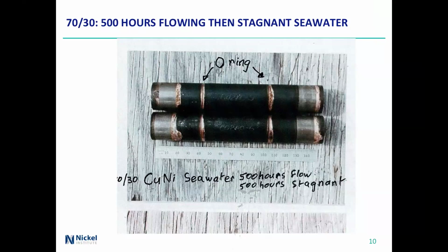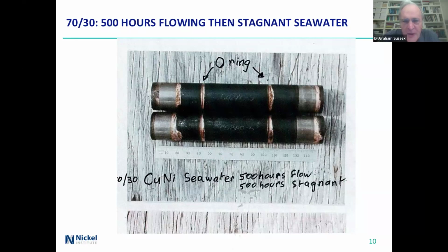Okay, this is a 70-30 copper nickel, and in the crevice up there, there is just corrosion going on because it's not completely inert. But the service is 500 hours flowing seawater, 500 hours stagnant. Stagnant is when it starts to go badly. The next picture, which I don't have, after 3 years, showed that there was corrosion going on all across the whole surface, which is not bad, but it was significantly the beginning of attack.